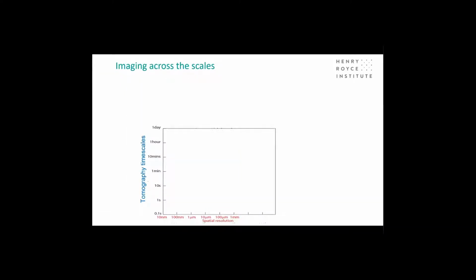I just thought to give a bit of an overview, it's helpful to plot tomography timescales on one side against spatial resolution on another. And synchrotron beamlines, as we've already seen, can work at very, very fast acquisition rates. Since, as we saw in the last talk, you can have acquisitions of each projection in fractions of a second, maybe a millisecond or so. And so if you need 1,000 projections to make an image, that might be 1 second for a tomograph. But of course, remember that in a synchrotron, you're rotating the sample. So your sample is also rotating once every second. And so there are some geometrical restrictions to the time at which you can take tomograms.